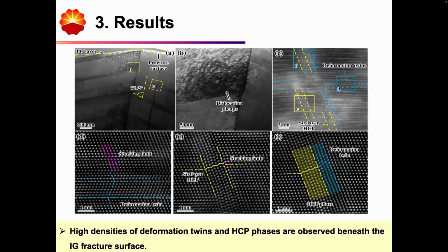Then we extracted the cross sections highlighted as C regions. With deeper analysis of the C regions, we can see it's actually some cross sections between the HCP phase and deformation twins. We also observed some HCP phase together with the deformation twin.